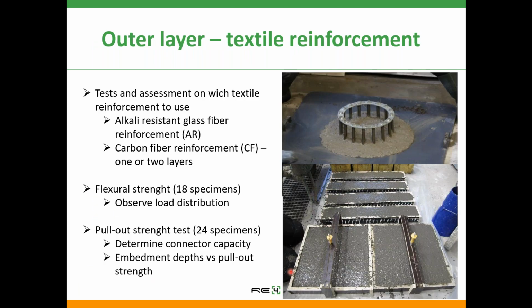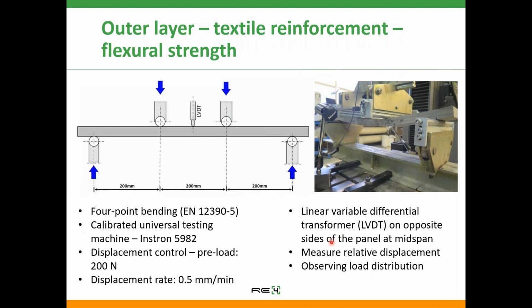So the next step for us, when we had developed a self-compacting concrete and a high-performance concrete that we were satisfied with, was that before upscaling at CREAG, we wanted to test which type of textile reinforcement to use in the outer panel. Therefore, we set up a test scheme where we produced test specimens using much smaller molds than they did at CREAG, for flexural strength tests and also pull-out strength for these anchors, these pin connectors. We used two different textile reinforcements, alkali-resistant glass fiber and carbon fiber, and with carbon fiber we tested 1 or 2 layers. In total, we tested 42 specimens.